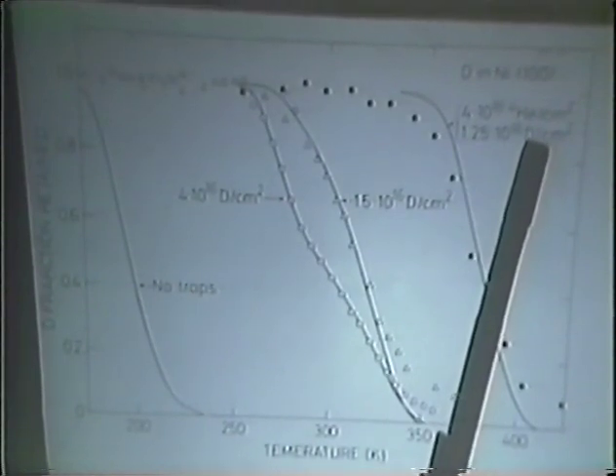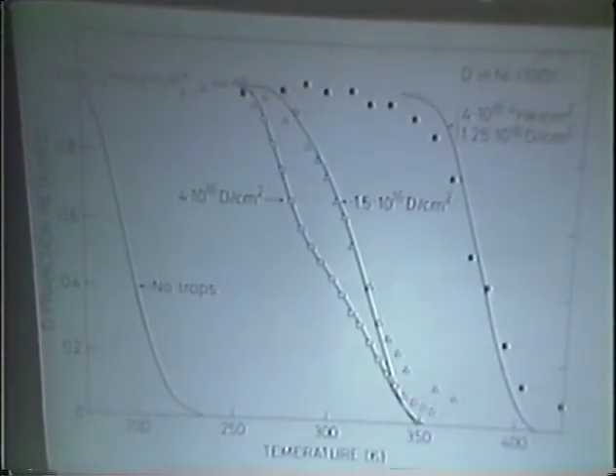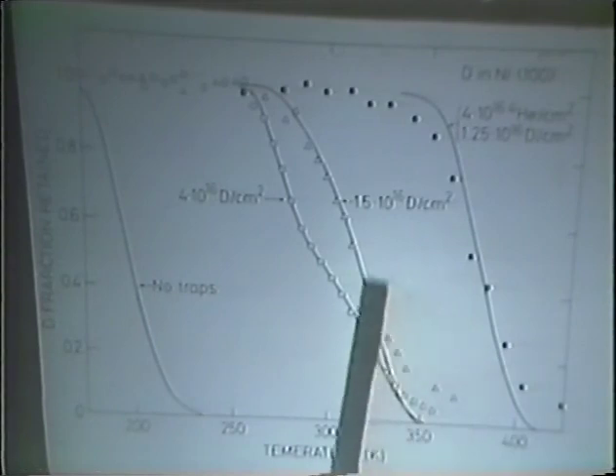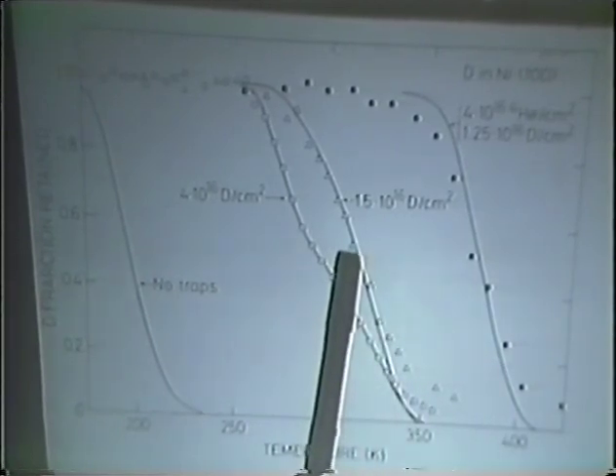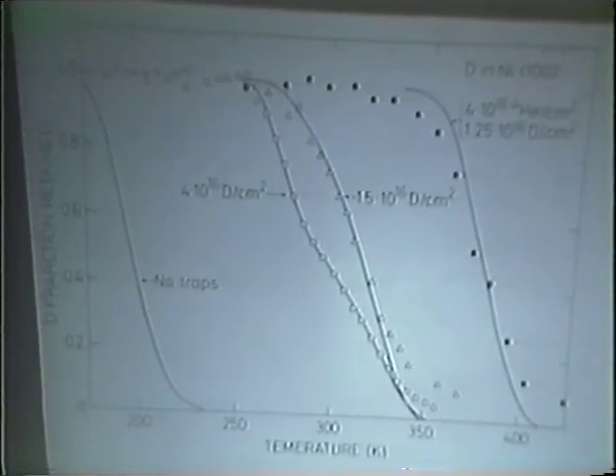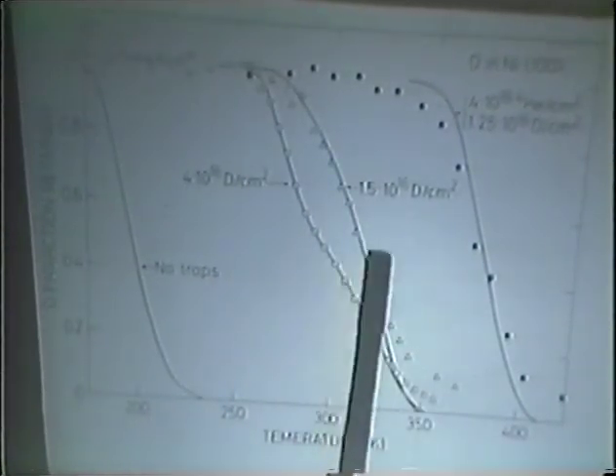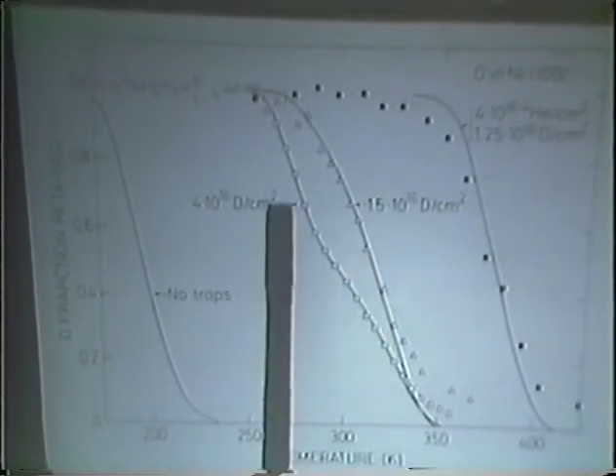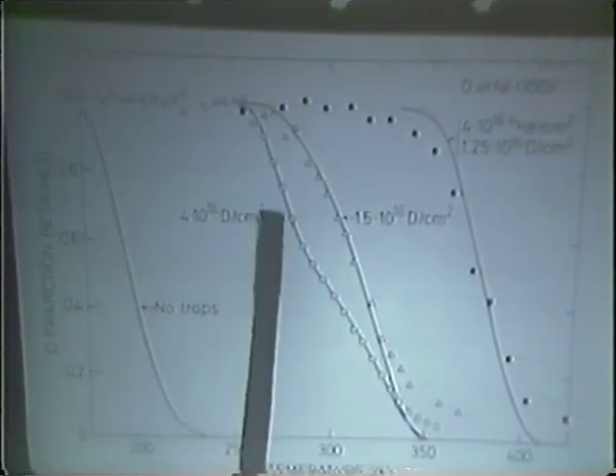The strongest traps we have observed are in the case where we pre-implanted with helium prior to the deuterium implantation. That creates a dense array of helium bubbles in our crystal, which has been observed with transmission electron microscopy. I should also say right away up here that this state is associated with hydrogen trapped to the internal walls of these bubbles, with a mechanism similar to chemisorption on the surface. The second state here, where we only implant deuterium, we associate with hydrogen trapped in vacancies. And you can then see that we get a lower temperature stage down here if we increase the amount of deuterium implanted. That is in fact associated with multiple occupancy of a given vacancy.